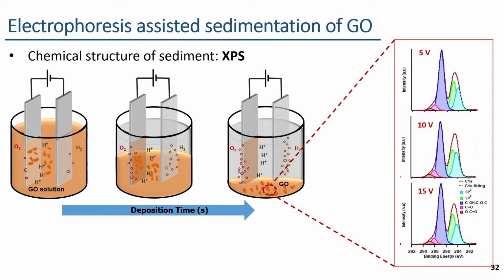However, the amount of basal plane oxygen functionalities in these sediments is less than the total amount of oxygen functionalities present in the GO coatings obtained after the sedimentation process. So, during the sedimentation, smaller GO particles with a smaller amount of oxygen functionalities are protonated and sedimented at first. However, the larger particles with a high amount of oxygen functionalities get protonated and sedimented later, because they have a high negative charge and the protonation is difficult.